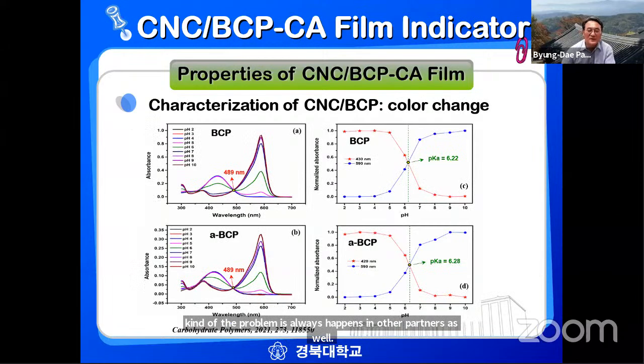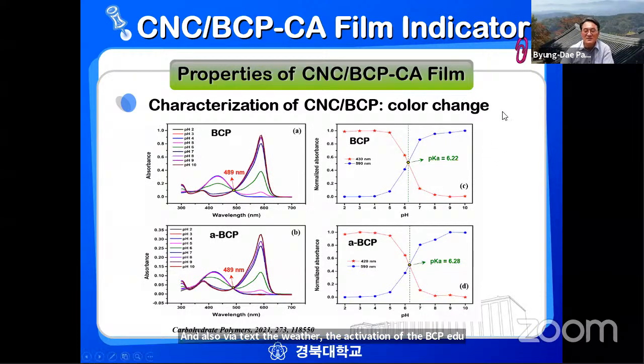And also we checked whether the activation of the BCP had any influence on the color changes, using UV-visible spectroscopy. We have the control BCP and activated BCP, and put them in different bromocresol purple solutions from pH 2 to 10. And then we measured the absorption of these peaks, and the wavelengths are the same, 489 nanometers, either activated or control. Also the normalized absorption is pretty much the same for activated BCP and control BCP, and the pKa shows only a little bit of change, almost the same. That means the activation does not have much impact on the color change of bromocresol purple.